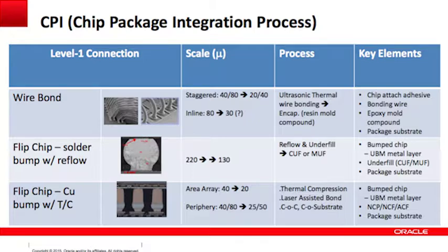And this bump is offering like 130 micron pitches, but it reduced the long wire length to very short. So it goes to typically about 100 micron long, and just 60 micron between chip and package. So it helps a lot with electrical performance and mechanical durability. And this is not enough. So change it to copper, and it can support even 20 micron with a tiny pillar, a copper pillar. And the processes to make it happen are wire bonding technologies and flip chip attach by reflow or thermal compression and other new technologies.